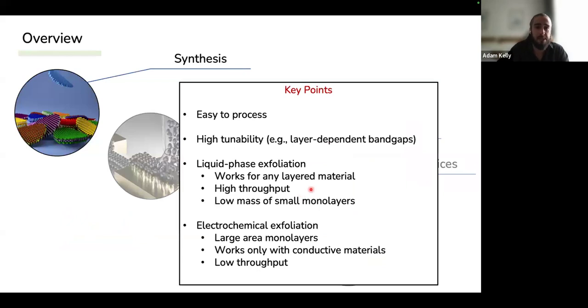So the key points for the synthesis: these materials are easy to process. We have very, very high tunability across them. The liquid phase exfoliation technique itself works for any layered material. We have high throughput. However, we get a low mass of small monolayers. Electrochemical exfoliation gives us large area monolayers, but it only works with conductive materials.